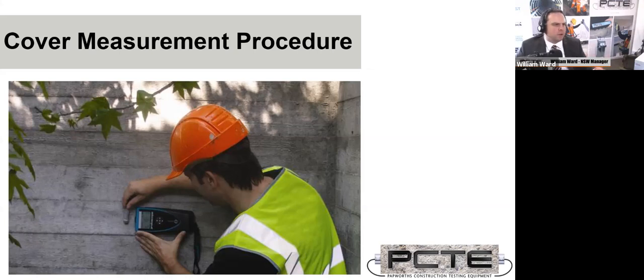Essentially, debonding, delamination in general is not going to be visible with your GPRs. A small air separation in between two materials doesn't change the response to a GPR very much at all. Now, if you've got enough air there, like a void form, a polystyrene void form, or an open void, it's quite easy to find those layers with a radar, but just fine delamination between carbon fiber and concrete, or within concrete, like with the expansive corrosion of reinforcing steel, you're not going to pick that up very effectively with GPR unless it's quite pronounced. And I wouldn't try and do it for the carbon fiber. I'd use some form of sonic test for delamination. Nearly every sonic or seismic survey technique is absolutely excellent at finding delamination.